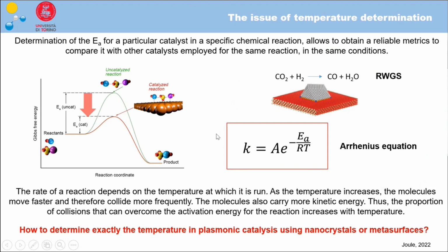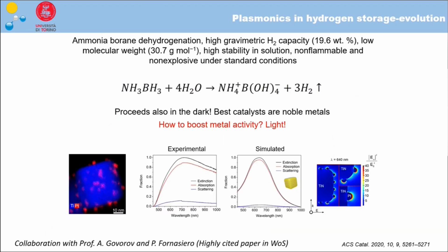On another note, it's also very important to determine the temperature that you generate in the system, because of course the reaction rate depends through the Arrhenius equation on the temperature that is generated. So understanding the conditions generated in situ during the light irradiation is very important to determine whether we're driving the reaction using only photoexcited carriers, only an increase of temperature, or both effects. And it's interesting also to have the possibility to use both effects, so we can speed up the reaction with in situ generated high temperature, and then maybe with energetic carriers we can modulate the reactivity and the productivity of our catalysts. And here I would like to show just one example of this case.